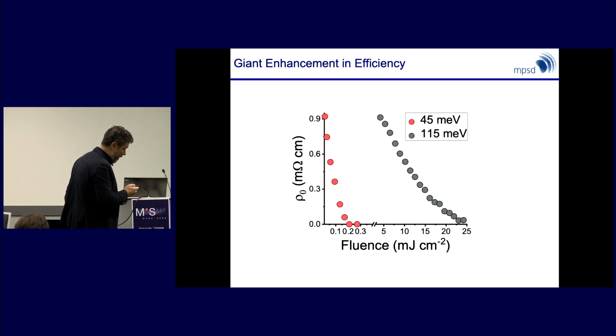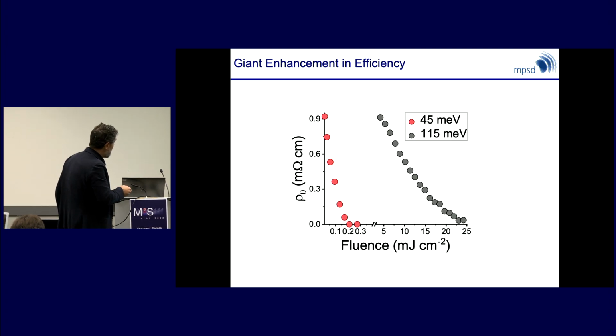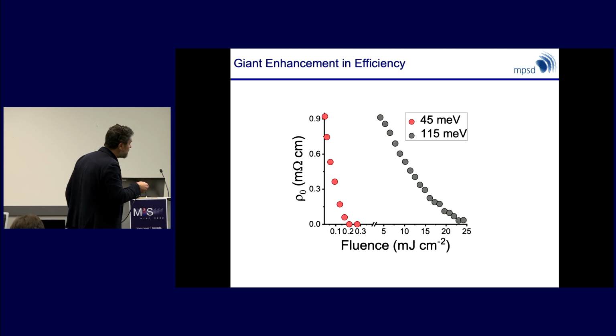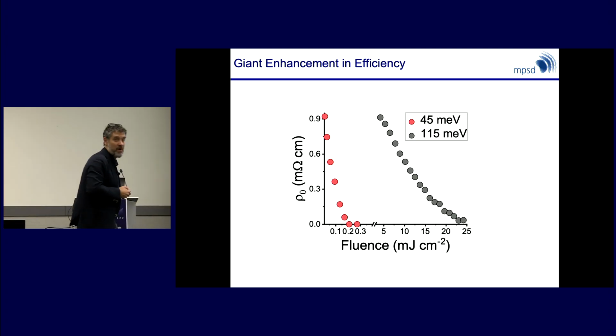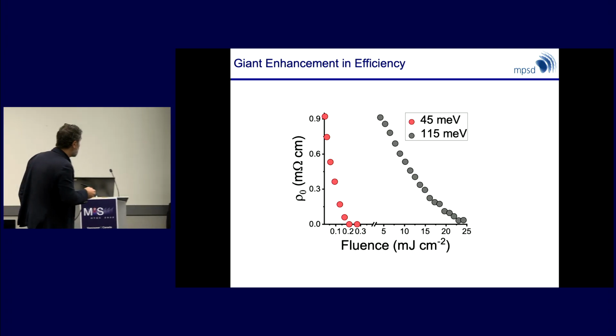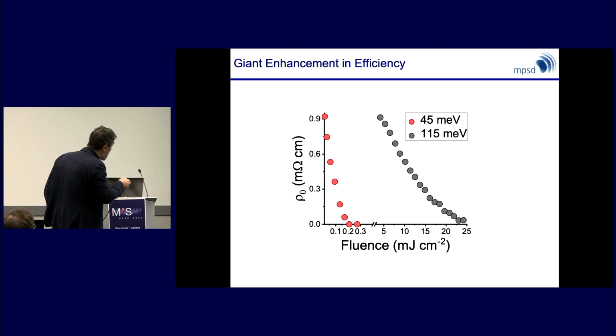This is well shown. So this is the way we would plot rho 0 of the photoinduced state as a function of fluence. When you pump at 7 microns, what you found is that you never reach anything in the vicinity of 0 if you don't pump with at least 20 millijoule per square centimeter. With this new method, pumping at 45 meV, we can reach the equivalent of something that is suggestive of zero resistance at 200 microjoules per square centimeter.